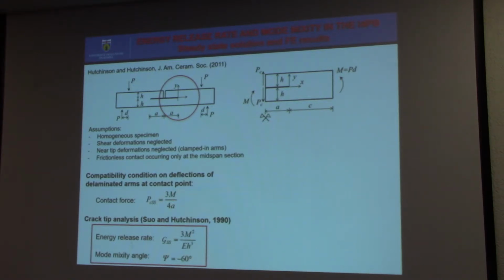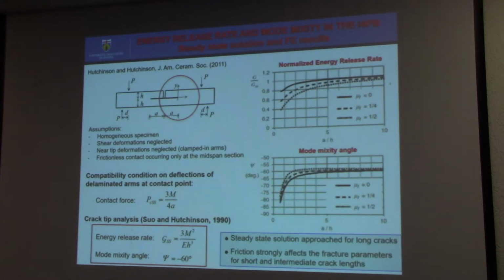So you see that the mode 2 component is much larger than the mode 1 component in the regular four-point bending test. They also performed some finite element calculations, and here you see the normalized energy release rate and the mode mixity angle as function of the length of the crack. And the different curves correspond to different values. They treated the problem assuming Coulomb friction, and they considered different values of the friction coefficient.